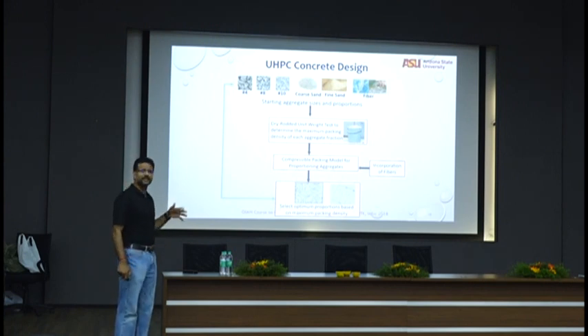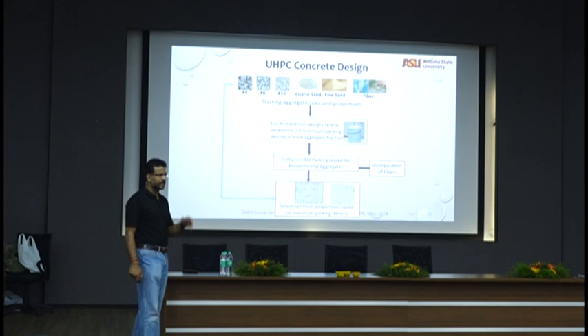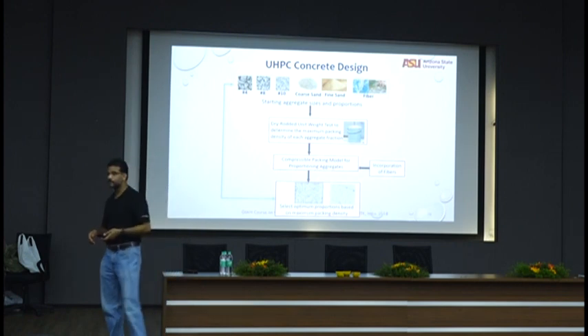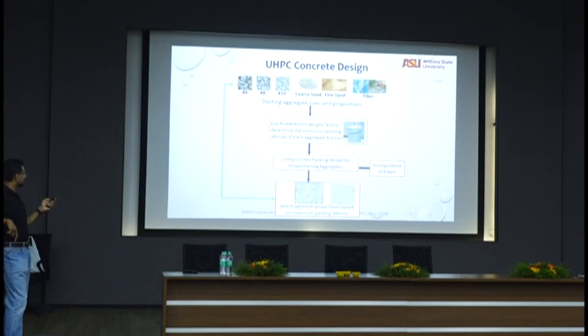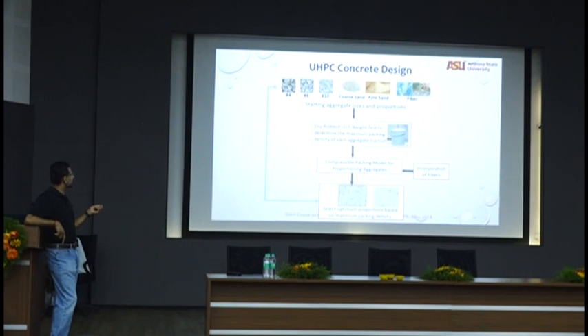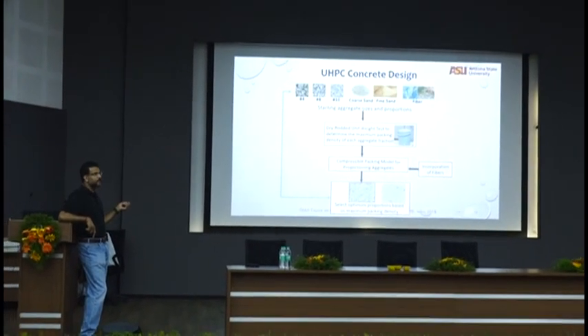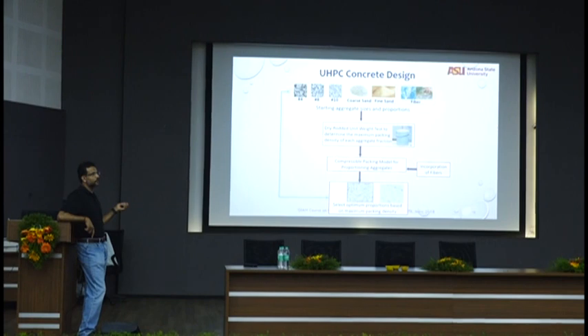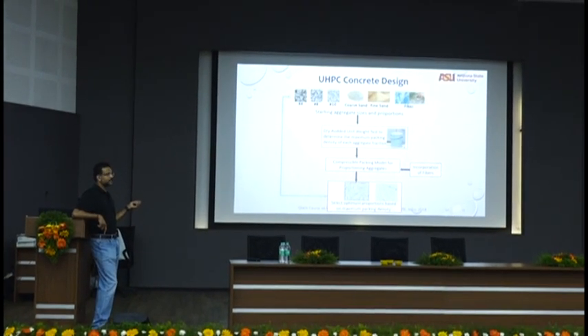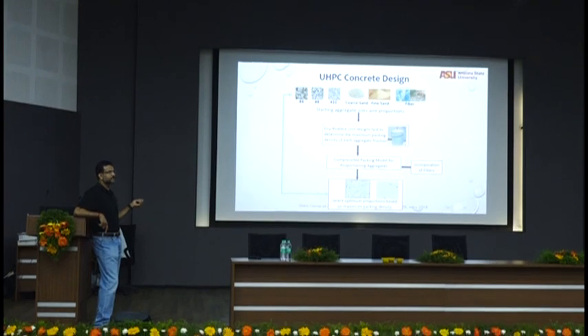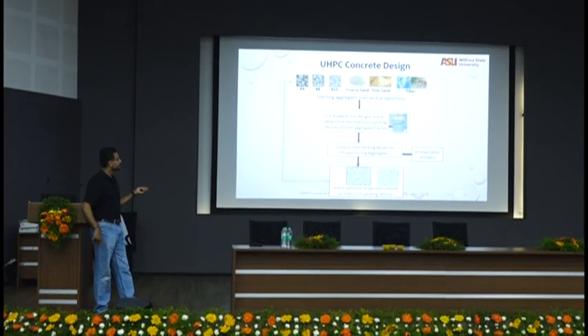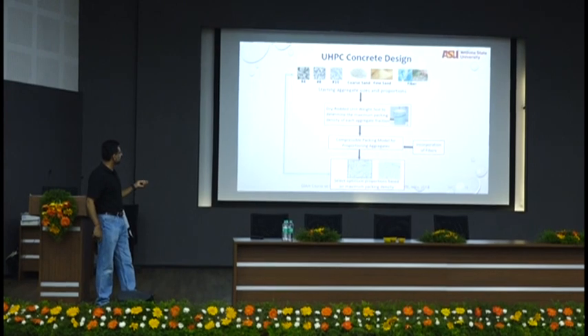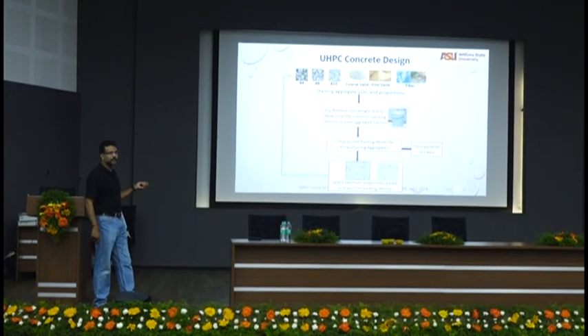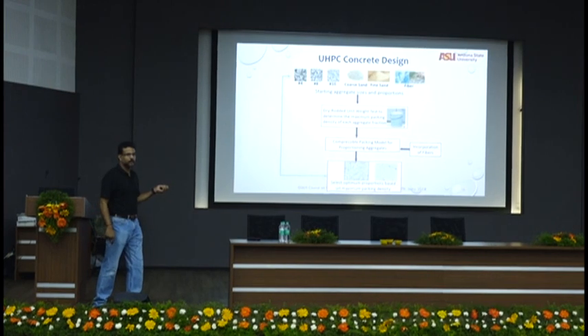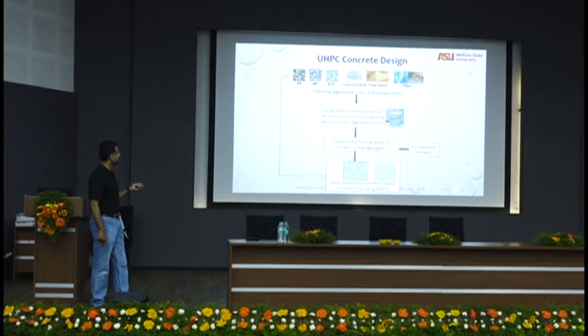I haven't seen many UHPC publications or any applied UHPC projects where people have used coarse aggregates, but we have indeed used aggregates passing 4.75 millimeter retained on 9.5, passing 2.36 retained on 4.75, and passing 2.36 retained on 1.2. Then we used a coarse sand and a fine sand. Coarse sand is 600 microns, fine sand is 300 microns, or 800 and 400, one of those. And then we used steel fibers.